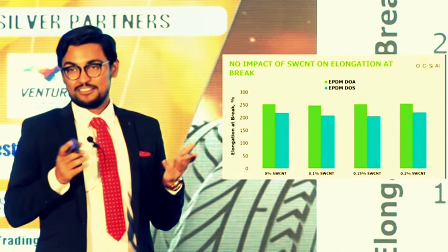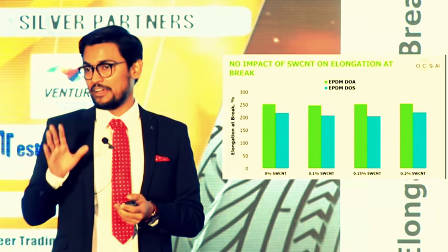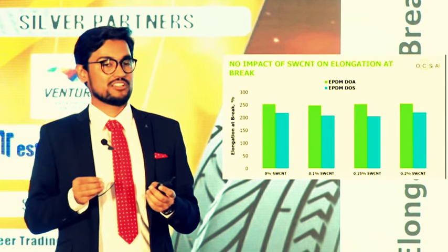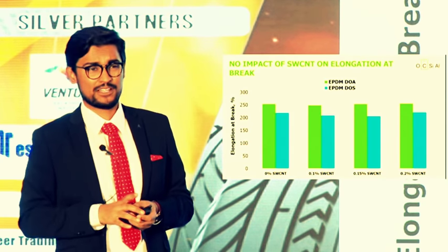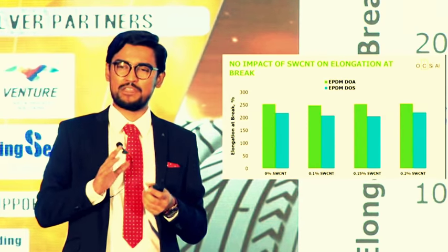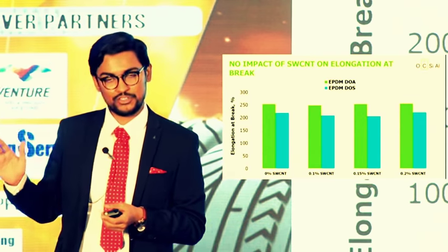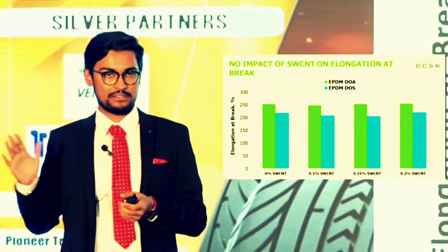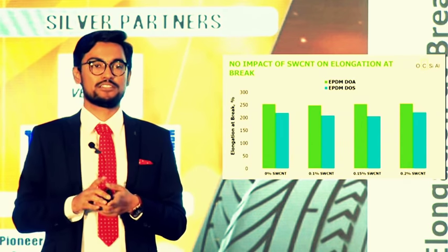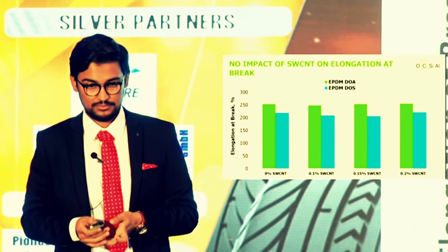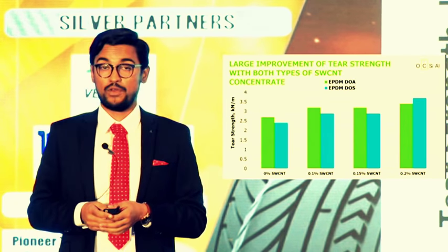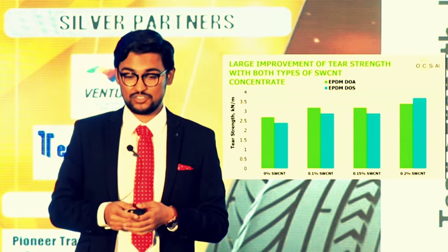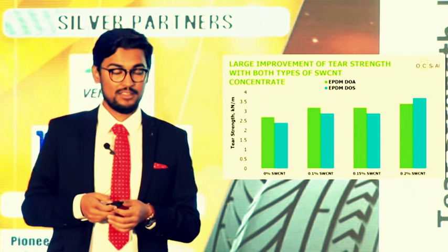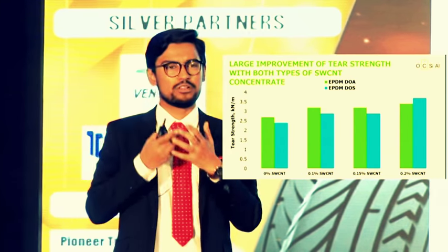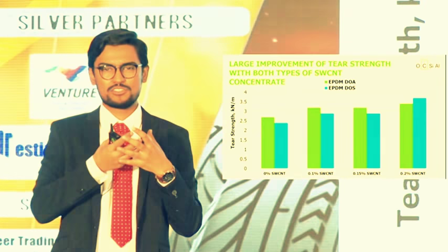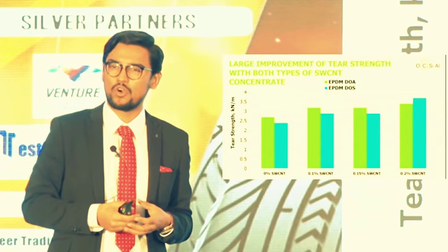And surprisingly, there was no adverse effect on elongation at break. The maximum effect we observed was in the range of 0 to 5%. Again, you have to compare this with other traditional material, like carbon black, when you add it, what it does to your compound. There was a very good improvement in tear strength, as you can see. This is attributed to the three-dimensional percolating structure I just showed and talked about.